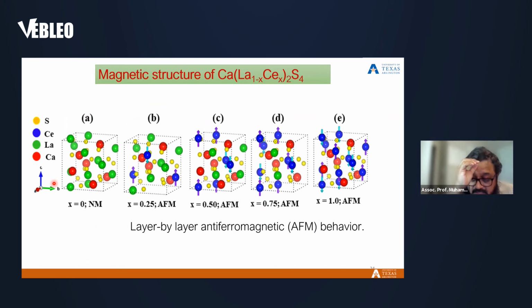Also, we check the magnetic state when there are no cerium atoms. X equals 0, this is non-magnetic. As soon as ceriums are incorporated, the cerium atoms within the structure started showing antiferromagnetic behavior. Then we start calculating the electronic properties. We will start with the calcium lanthanum sulfide when X equals 0.